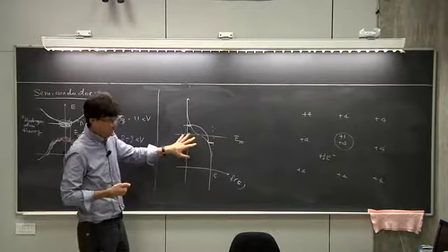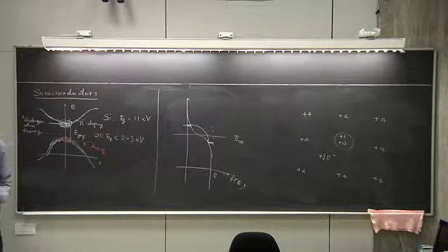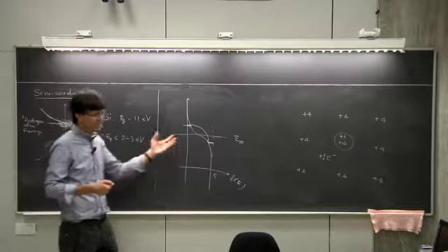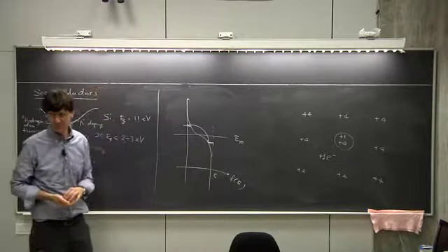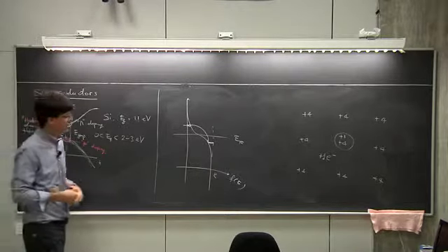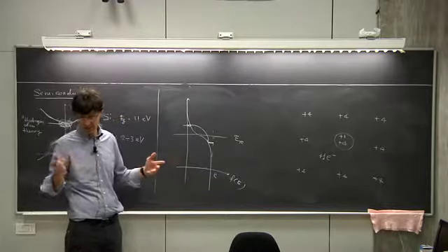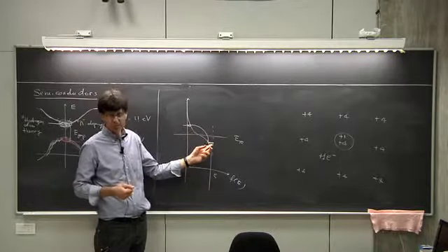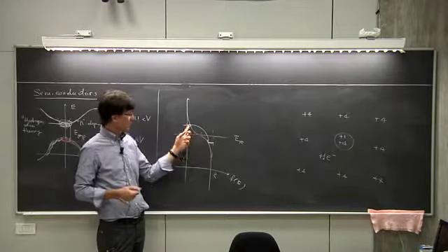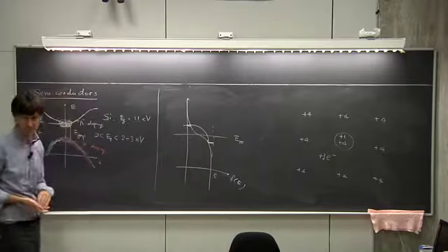So this is the most stable configuration of electrons at a given temperature. That's the way you derive the Fermi-Dirac distribution. You derive it in such a way that this is the minimum of your free energy. Okay? There's no better configuration than this one. Whatever you do here, you're going to increase your free energy. Of course, not the energy, because as you argue, it would be easy to minimize the energy. Just take an electron from here to here, you're done. You lose entropy in doing that.